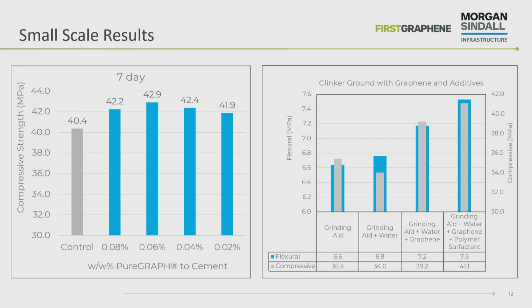We also looked at the effect of the grinding aid. So the grinding aid is just like a liquid. It's just like water, it's very low viscosity. So when we added graphene into that and then dispersed it, the viscosity shot right up. So we had to add some extra water to get that flowable again, because it had to pass through existing equipment on the Breedon cement plant. The one thing we wanted to do is use as much existing equipment inside the cement plant as possible. So we were doing this dispersion, but then the viscosity shot right up, so we had to add some extra water to keep it flowable.